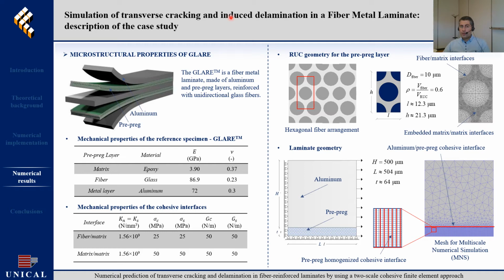Then, the geometry of the simulated portion of laminate is shown, together with the mesh configuration adopted for the multiscale analysis. In particular, the mesh adopted for the prepreg layer is a mapped mesh with duplicated nodes, such that zero-thickness interfaces with homogenized cohesive properties are pre-inserted along the vertical mesh boundaries.